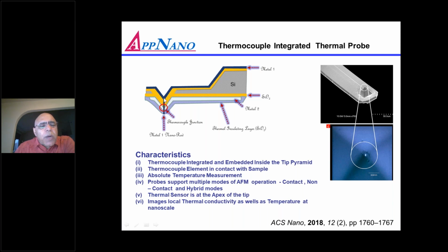Then we have a proprietary technology where we can make a nanorod using the same metal on the back side. And so this is metal 1, metal 2, and if you see here, the thermocouple junction is right here, and the whole thing from the front is covered with the insulator, and the nanorod comes out of the insulator. So your sample is actually, this nanorod is actually in contact with the sample all the time when